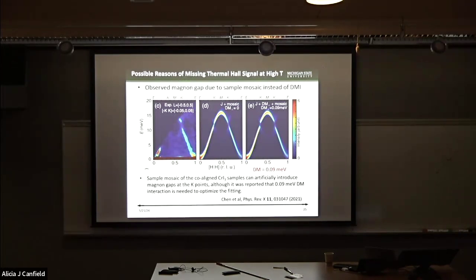mosaic, and then they found that the magnon gap is much smaller than what they found initially in the 2018 PRX paper. And they found that, as a matter of fact, the sample mosaic contributes to the magnon gap opening at the K point. So for instance, I did some simulations. The middle figure shows the linear spin wave simulation without the DM interaction, but considering the sample mosaic, an 8-degree sample mosaic. We can see that indeed there's a magnon gap opening at the K point.